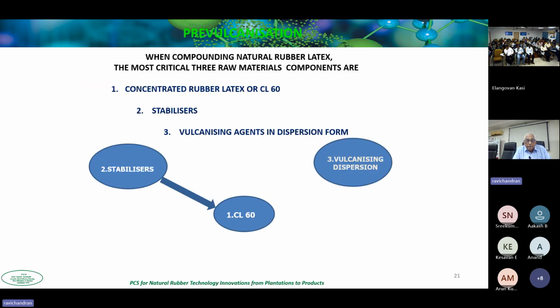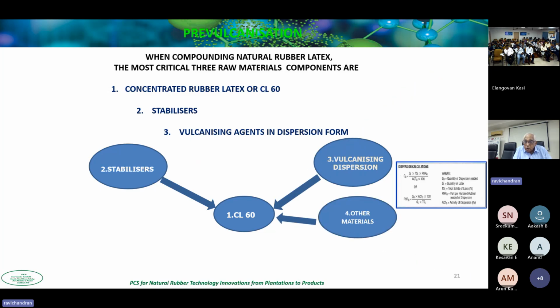So when we're compounding latex, you have the latex, you add the stabilizers first, stabilize the latex, then you add the vulcanizing dispersion, and then you add the other materials. So that sequence follows of doing the pre-vulcanizing. I've given a little calculation on how we actually calculate the quantity of dispersion. We make the formula in dry rubber on a DRC basis, but then we prepare the dispersions at 50% aqueous, and we have to add it into the latex.